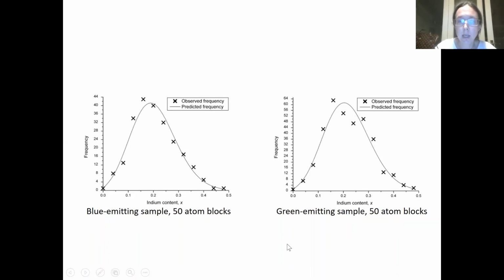And if we do a statistical analysis, we find that the probability that these distributions are random is really quite high. What that's telling us is we haven't got any evidence for the formation of these indium clusters. We haven't got any evidence of the formation of these blotches that we thought we saw in the TEM, but that then we wondered whether they'd been caused by the electron beam.